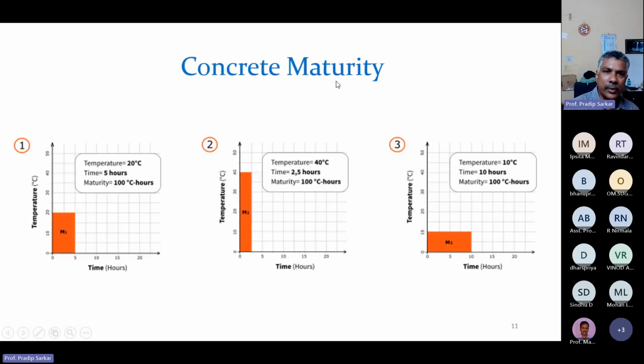So what is concrete maturity? You see here the temperature on the y-axis and time on the x-axis. The integration of this temperature-time history represents the maturity. So here this is M1. M1 is a constant temperature of 20 degrees centigrade over a 5-hour time. So 5 hours times 20 degrees is 100 degree centigrade hours. This is the maturity.